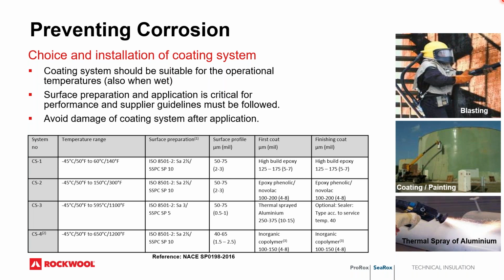So NACE has outlined specific procedures for dealing with surfaces at various temperatures to help mitigate the corrosion situation that we often face in these facilities. So of course, your coating system should be suitable for the operational temperatures, so you've got to check your coatings. Surface preparation is critical. And then of course, once it's all coated, you do have to avoid damage of the coating after application. So all these things can be factored into an inspection and test plan in relation to controlling CUI.